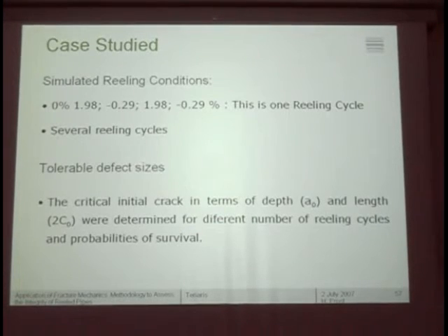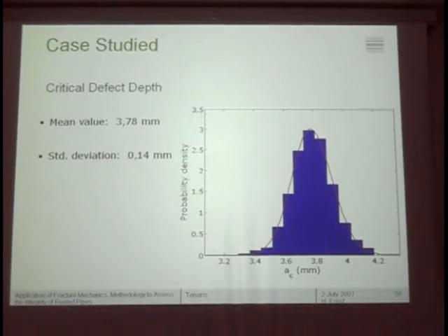So with all that, we simulated reeling conditions of 0, about 2%, minus 0.3, 2%, minus 0.3. Some people call this one reeling cycle, composed of two deformation cycles, and of course there is the possibility of running also several reeling cycles. And as you will see, this is the result of all what I said. This is the critical initial defect depth, you see here the distribution that comes out of the model with a standard deviation of 0.14 millimeters.